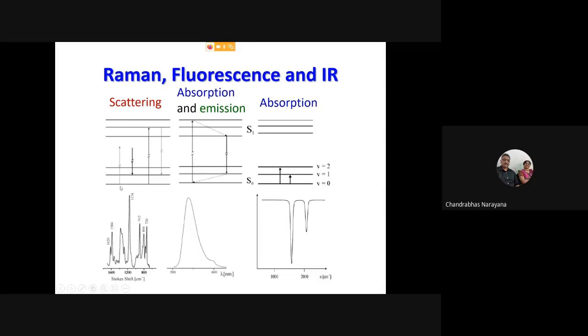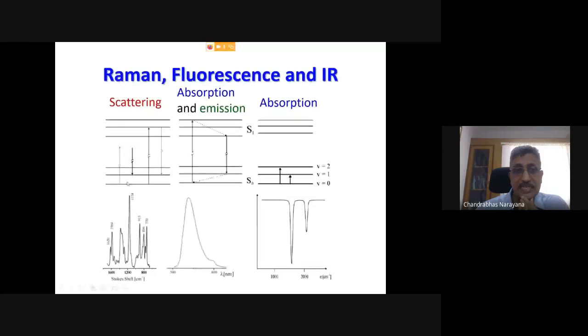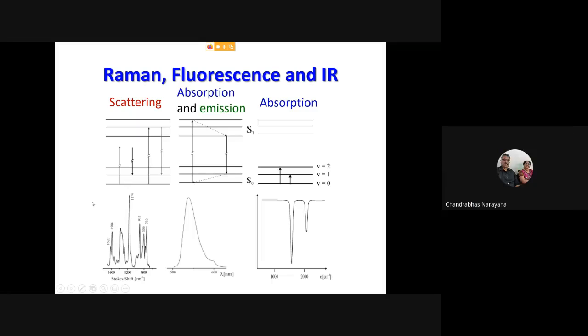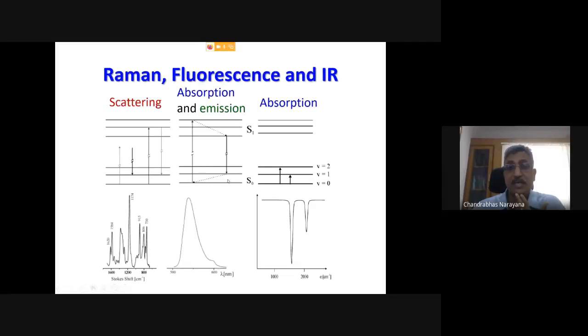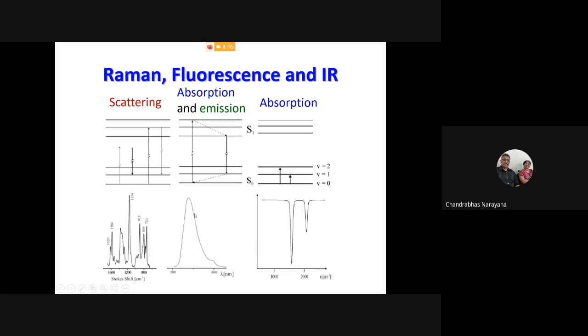Raman is actually a transition between the excited state and the ground state, and only the difference between the vibrational states. So this gives me very sharp peaks, and it is an inelastic process because it is not direct absorption. Whereas in fluorescence, you are actually going to the excited state and coming down to the ground state, so you span the complete energy states. So you get a broad band. And if you zoom up, you will see Raman scattering sitting on top of it.